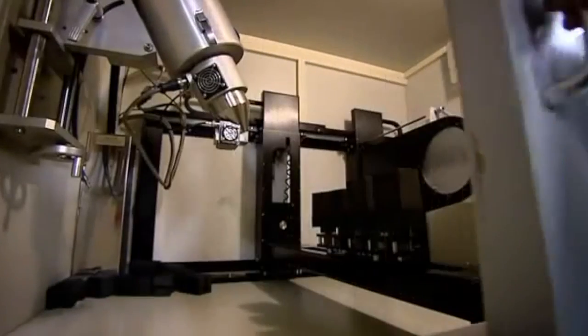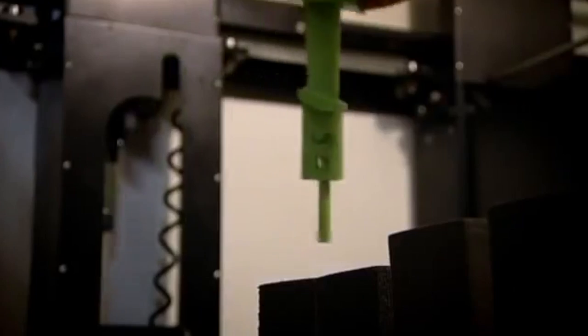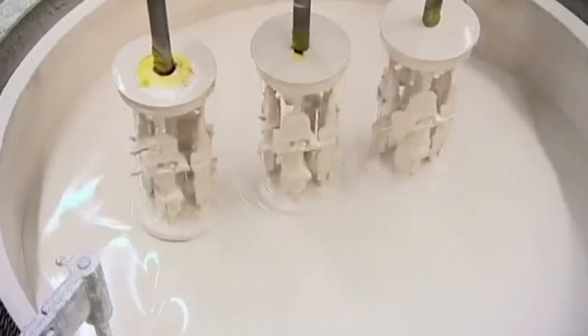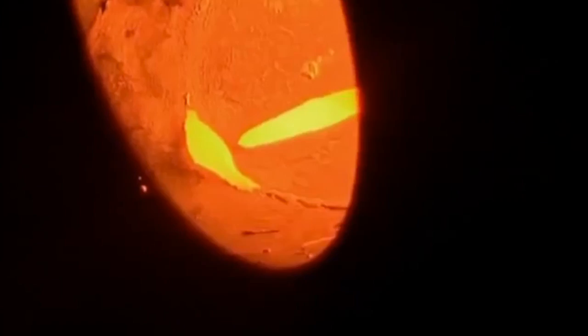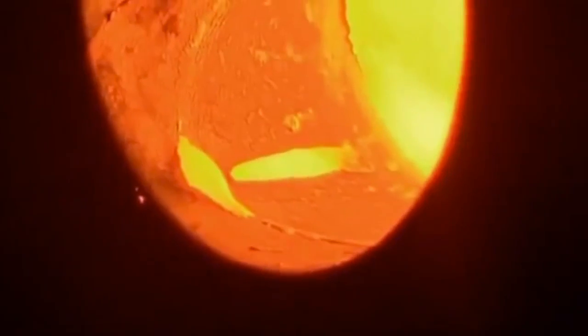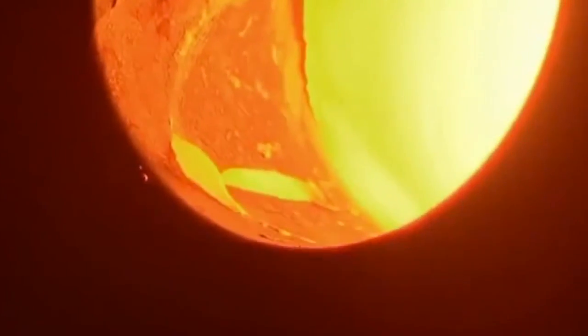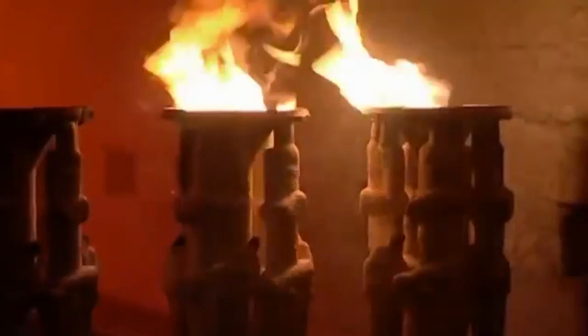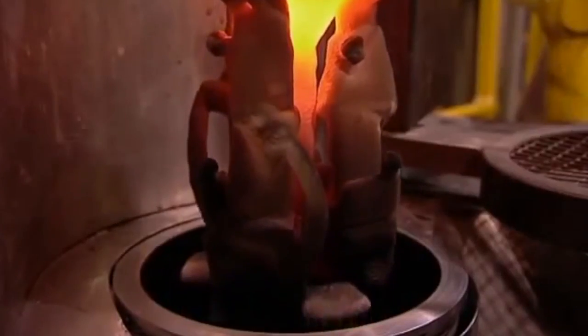Once the wax models are made, they are then X-rayed to check for any imperfections before they are covered with the investment. The next process is casting, where the nickel-based superalloy is cast into a single crystal. After the casting, each blade is inspected individually for any imperfections before machining starts.